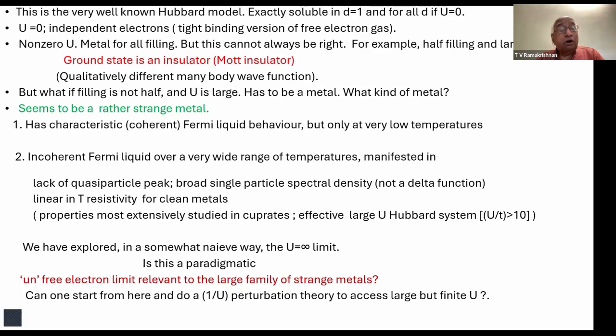Another experimental feature which is very odd is that a clean metal in this family has a resistivity which is linear in temperature. Now, it turns out that clean metals which are Drude-like also have non-zero resistivity. Copper has non-zero resistivity, platinum has non-zero resistivity at non-zero temperatures, and so on, even when it is very clean. And that is due to the interaction between the electrons and the lattice vibrations. Here, that resistivity is most likely very small, but in spite of that, there is a very large linear in temperature resistivity for clean systems.